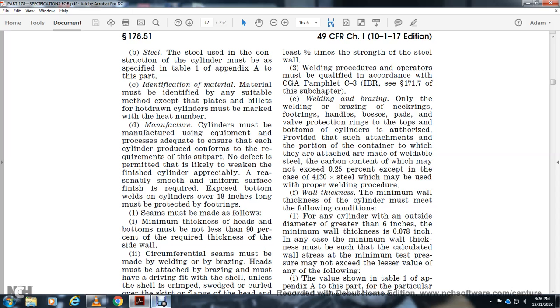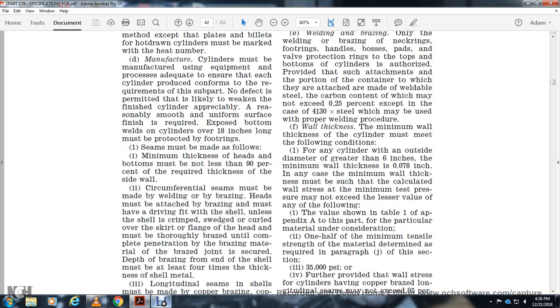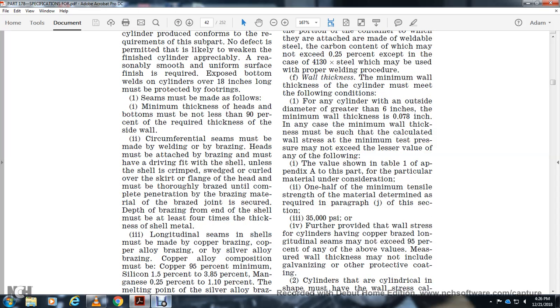The minimum test pressure may not exceed the lesser value of any of the following: the value shown in table 1 of appendix A for the particular material under consideration; one-half of the minimum tensile strength of the material as required in paragraph J of the section; or 35,000 psi. Further, wall stress for a cylinder with a head and copper braze and longitudinal seams may not exceed 95% of the above value. The measured wall thickness may not include galvanizing or other protective coating.